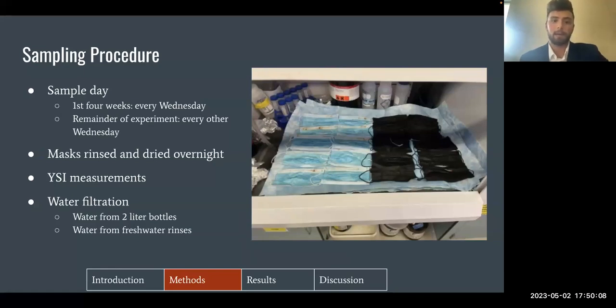The seawater from the glass bottles was probed with a YSI instrument to collect temperature and salinity data, and both the seawater from the glass bottles and the fresh water used to rinse each mask was collected and filtered as part of the analysis. I'll get into the water filtration in a bit more detail a little later on, but after the masks were dried overnight, they were placed in individual 1-quart Ziploc bags for preservation and taken to the marine toxicology and coral histology labs for dry weight and light transmittance measurements.